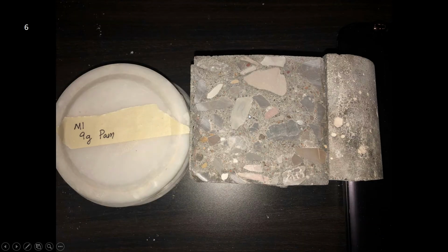Our sixth sample is 9 grams of PAM applied to the cylinder. This has had the most effect on the surface area. You can see it eating away and cracking at the concrete. And you can see also that it has started infiltrating the concrete along the edges of the cross section.